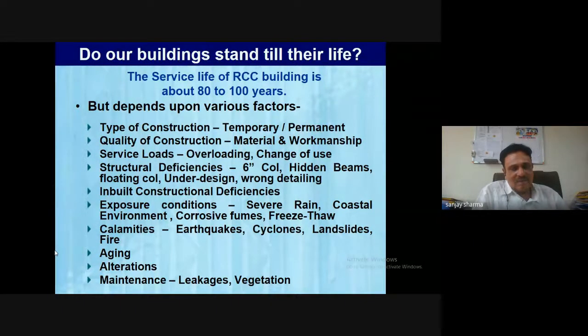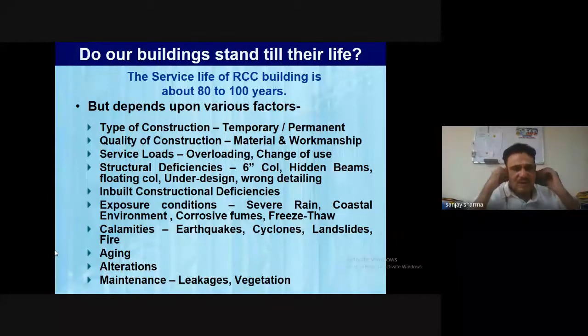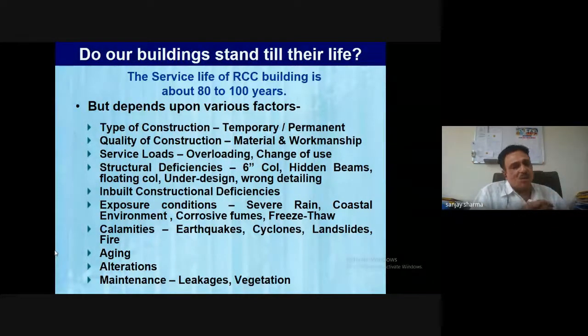And basically, as they went above, they carried out construction up to four stories, and it was found that cracks started appearing in the columns and in the slabs also. So basically, the first thing that always comes to mind is the quality of the work. Quality of the work was checked using NDT techniques, mainly the rebound hammer and ultrasonic pulse velocity. But then it was found that the quality was okay.